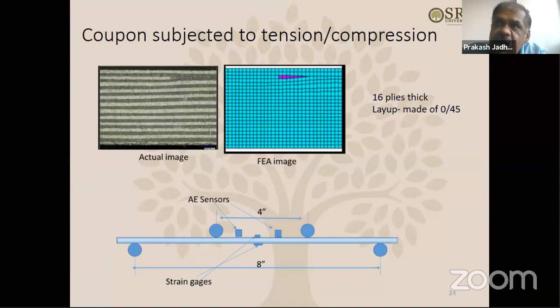To talk about this initiation of cracks: when any coupon or any blade is tested, even in blade testing, the test happens so fast, in a fraction of seconds, and then you directly see the failed blade. When you pick up the blade and look under a microscope, you see a big crack which initiated somewhere and then propagated elsewhere. So you don't know when the crack initiation started, at what load it started. So how do you find the crack initiation? That is a big question.